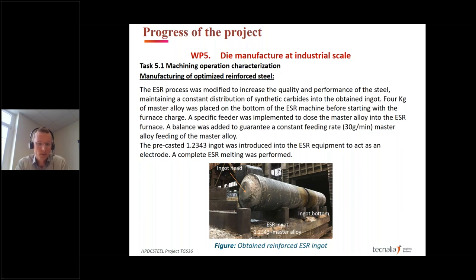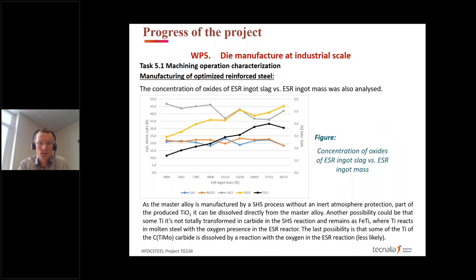So we had the initial composition of the master alloy before starting the ESR process. There was a kind of premix mixture given on the bottom, on the core plate of the crucible of the ESR plant. And then we had the continuous, constant feeding of 30 grams per minute of master alloy during ESR remelting. So you can see here, this is a result from the plant. We also analyzed the slag composition, and you can see here the analysis of slag composition on the left and right axes, and on the x-axis we have the ESR ingot mass.